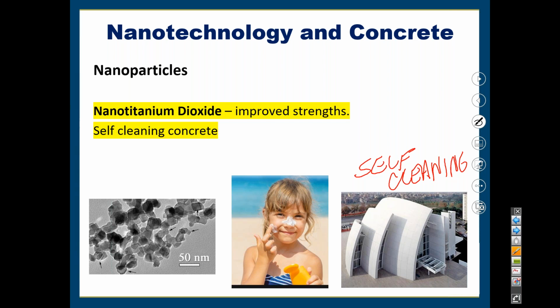So initially, the intent was just to be able to keep those precast panels, those are precast panels, by the way, bright white. And so they used this titanium dioxide cement so that it breaks down the pollutants that come into contact with it, keeping it cleaner. But now they're further using and developing this titanium dioxide to also, the claims are that it could clean the air in cities and on highways where it's used. And so using it on a nanoscale also has been reported to help improve strength, mainly by virtue of it being a nucleation site, very similar to what we talked about, the nanosilica.